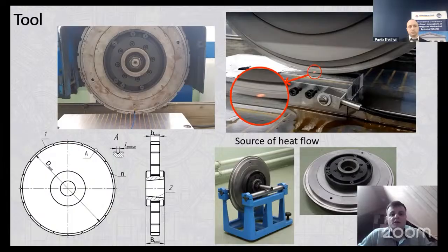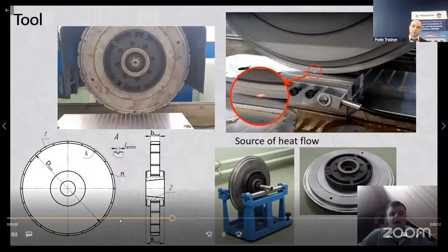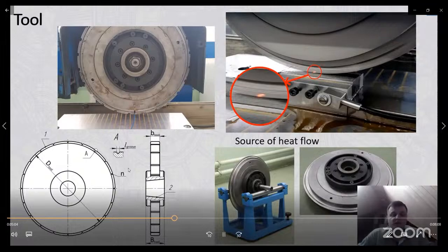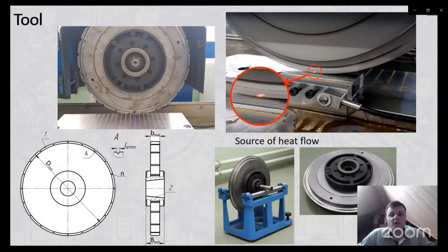The surface layers change the structure, physical, mechanical, and electromechanical characteristics of the metal, increase their hardness, decrease the grain size, and change the chemical and phase composition of the metal, and the magnitude and sign of residual stresses, which significantly affect the performance of machine parts during operation. A highly concentrated energy flow is formed in the area of contact of the tool with the treated surface during the high-speed friction in the friction treatment process. Stressed layers with a non-crystalline structure, white layers, are formed in the surface layer of the machine parts. White layers have increased hardness and viscosity, dislocation density, and residual austenite, crushed grain, and residual compressive stress are formed compared to the base metal.